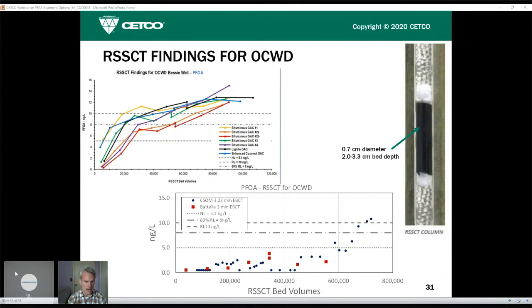I'll note that bed volumes can be a little difficult to compare when you're running a column system at different empty bed contact times. So if you assume that we had about a 3 times reduction in the empty bed contact time compared to GAC, we're still significantly processing more water before breakthrough with FLUORO-SORB.